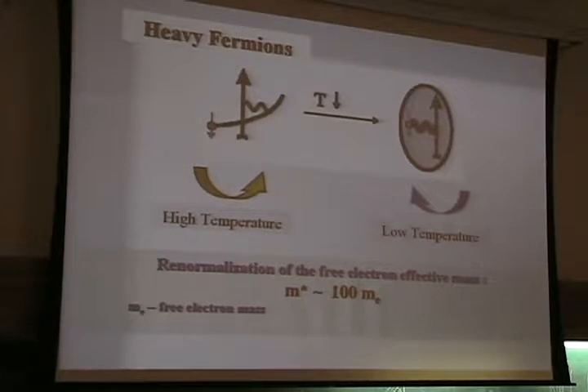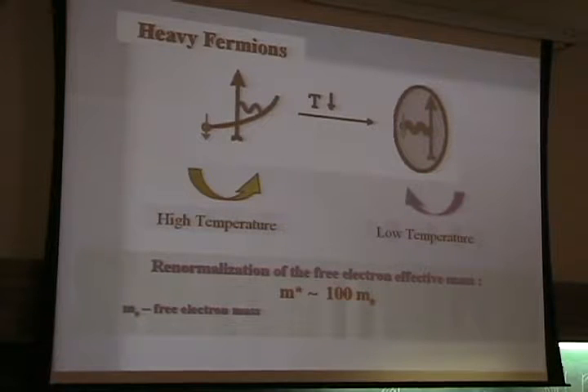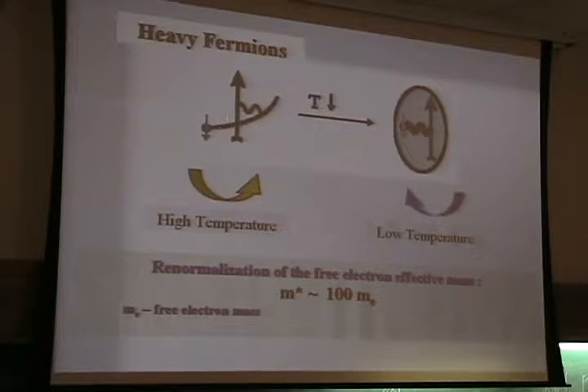In the case of intermetallic compounds, the kind of system we are interested in here, we have a collection of paramagnetic magnetic moments embedded in a Fermi sea, an electron sea, and not correlated. Below some temperature, they develop some correlation, and you have a very strong renormalization of the free electron mass that can be 100 or 1,000 times the free electron mass. So the definition of a heavy fermion material is mainly this: the electronic mass is renormalized in such a way that it becomes much bigger at low temperature than for normal metals.